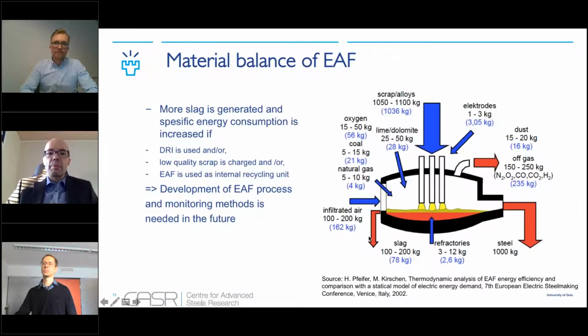And this increase depends on how much DRI is used, or if the ratio of low quality scrap is increased, or if the electric arc furnace is used as an internal recycling unit. All of these increase the amount of slag produced during the melting. But it also means that we have to develop the process and monitoring methods so that they will be more flexible with the different raw materials and the different energy sources in the future.